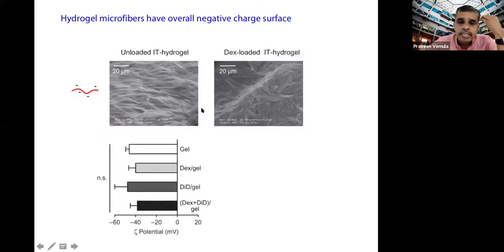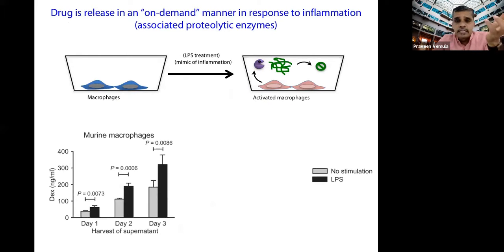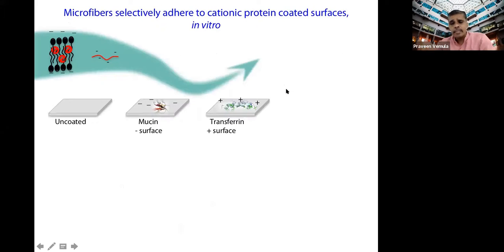Once we fabricated this material, you can see the micron-size fibers, and we loaded them with drugs and dyes and so on. Interestingly, all these fibers have a high negative surface charge, about -40 in zeta potential measurements. Again, they release the drug in response to inflammation. Then we wanted to see whether this material has the ability to bind specifically to the proteins expressed at the site of inflammation. So we took transferrin, which is known to be produced at the site of inflammation, and coated it onto a glass plate.